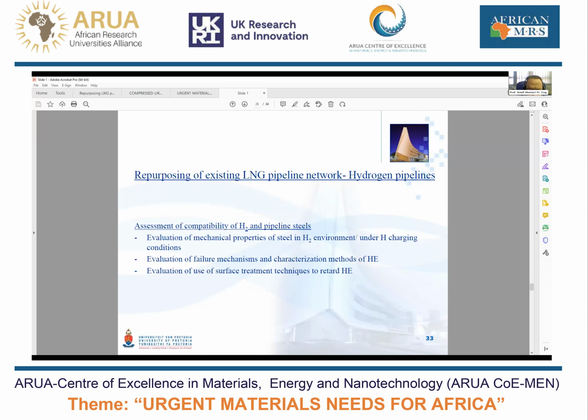So the mechanical properties in particular of these steels in the pressurized hydrogen environment need to be evaluated, and this calls for fairly sophisticated testing equipment. The test method will have to ensure that you have the pressurized hydrogen environment and that you've got the sample inside and that no hydrogen escapes while you are straining the material, and this calls for quite difficult experimental setups. Point is that currently in South Africa we do not have the facilities required to do this type of test. The failure mechanisms and surface treatments then also need to be evaluated in the laboratory.